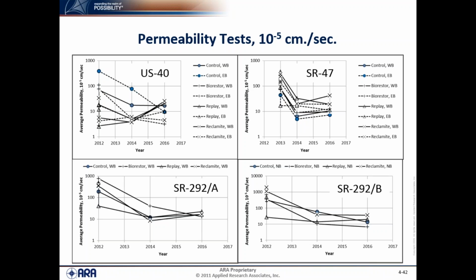So there's a lot there, and the field permeability test has significantly higher variability in the results than any of the other tests, as well as our condition surveys that we did over time. So the variation is quite extensive. But what you can see, if you look close, is a general downward trend in terms of permeability, which we would generally expect.